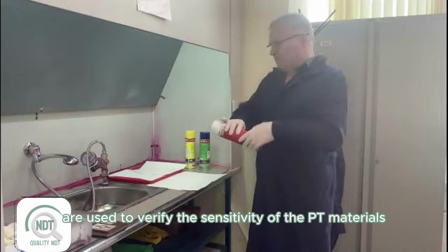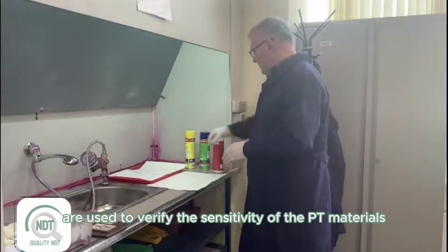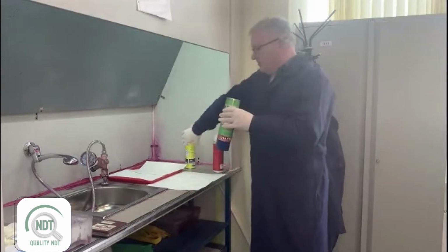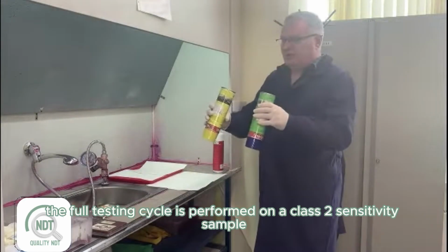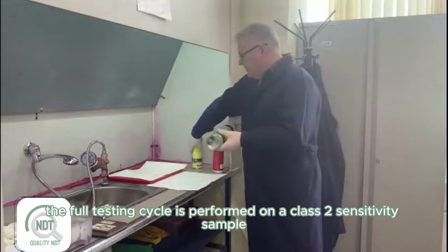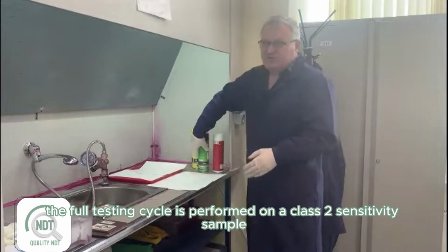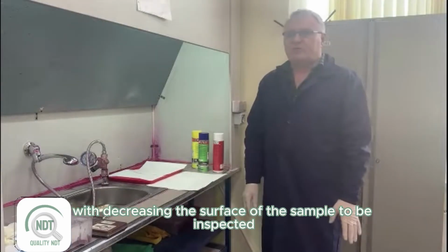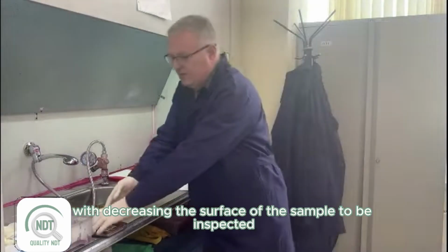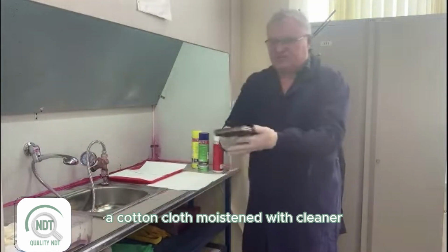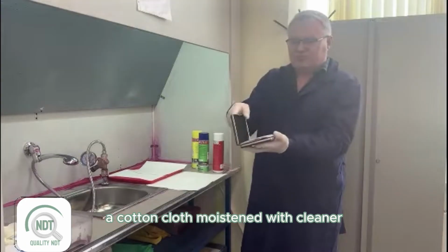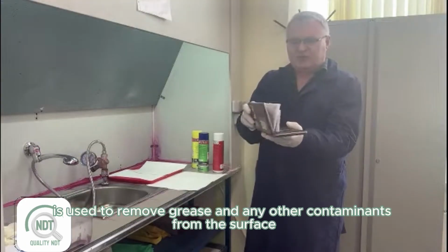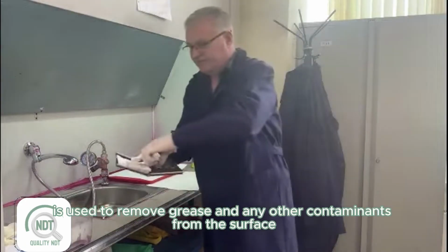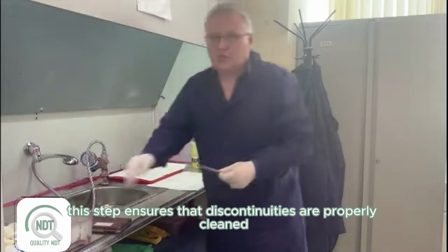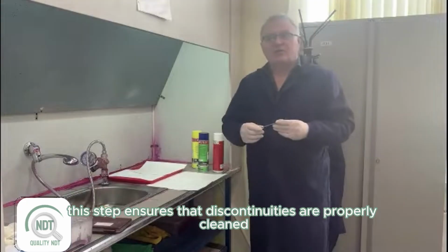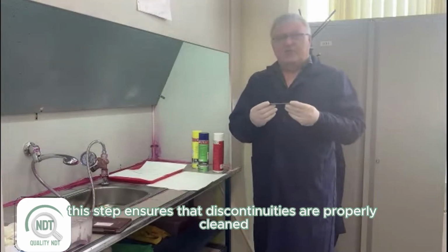Sensitivity samples are used to verify the sensitivity of the PT materials. To confirm their quality, the full testing cycle is performed on a Class 2 sensitivity sample. The inspection begins with degreasing the surface of the sample to be inspected. A cotton cloth moistened with cleaner is used to remove grease and any other contaminants from the surface. This step ensures that discontinuities are properly cleaned.